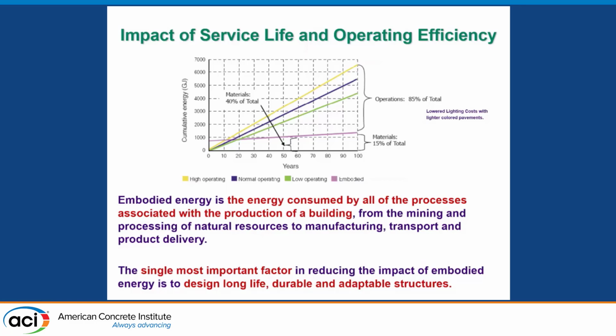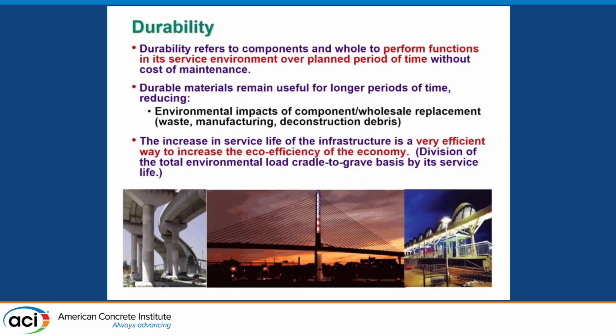So the way I like to look at it is I live very close to a highway. They've replaced that highway 6 times with asphalt in less than 20 years. The concrete pavement that is close by on a similar highway, put down 20 years ago, has never been replaced. So which one has the higher operating and CO2 levels? It's certainly the asphalt in this particular case. So when we look at embodied energy, which is another name for CO2, we really have to look at the total impact of the structure. And again, this is where I come back to service life and durability.